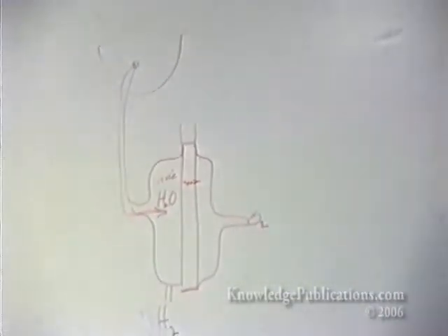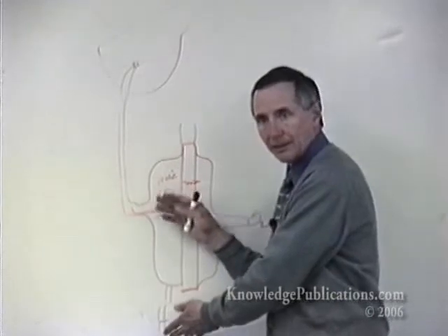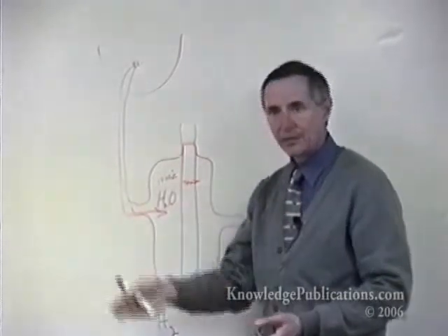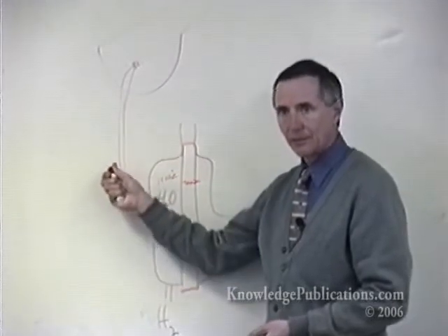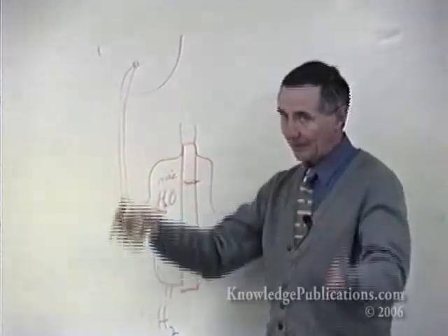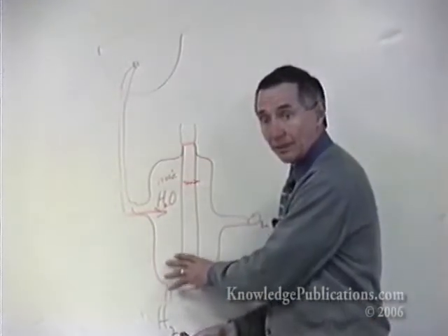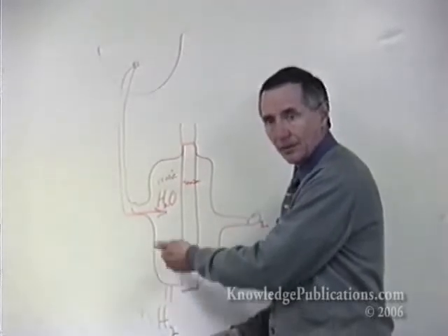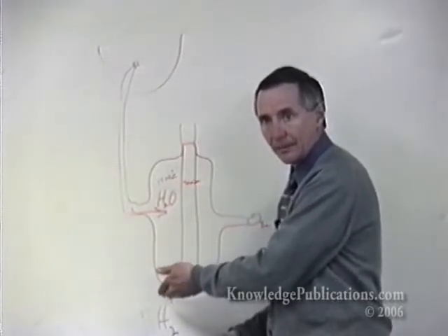The advantage of which is, and this is really important, that the efficiency of this operation electrically can be over 100% because you've substituted heat for voltage. You didn't get something for nothing. You didn't violate any of the laws of thermodynamics, but you can certainly get more BTUs of hydrogen out of this unit than you put in equivalent units of electricity by virtue of having added the solar energy.